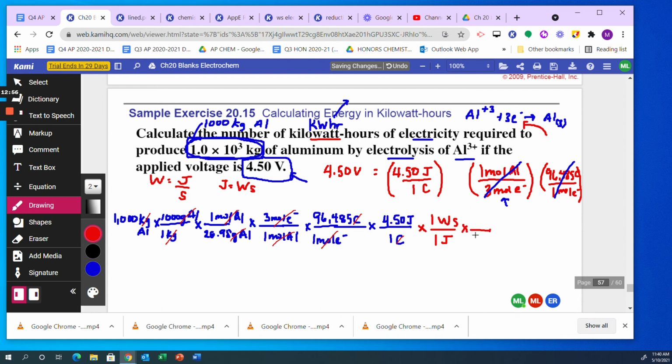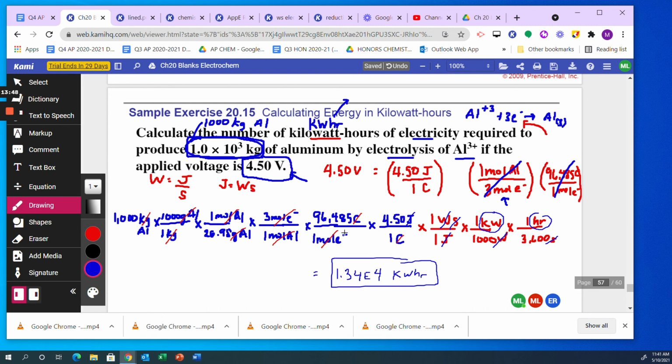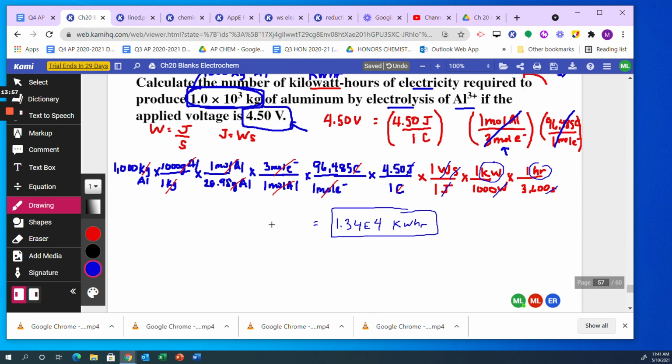So I need to convert watts to kilowatts. So 1,000 watts is 1 kilowatt, right? And then now I have to convert seconds to hours. 3,600 seconds is 1 hour. Okay, so when I'm doing the unit cancellation, joules is gone, watts is gone, seconds is gone, and I'm left with kilowatt hour, which is the amount of energy, right? So go ahead and do that calculation. You should get 1.34 e to the 4th kilowatt hour of energy to make aluminum from aluminum plus 3. So in your textbook, there is a practice exercise in 20.15. Do that on your own and see if you can get the right answer before you watch the next video.